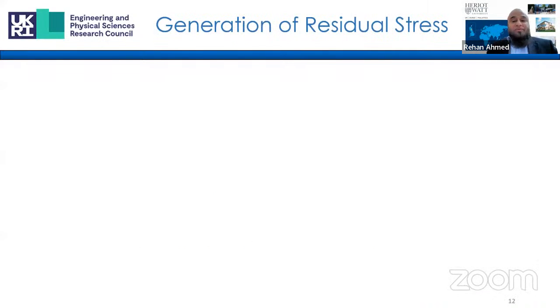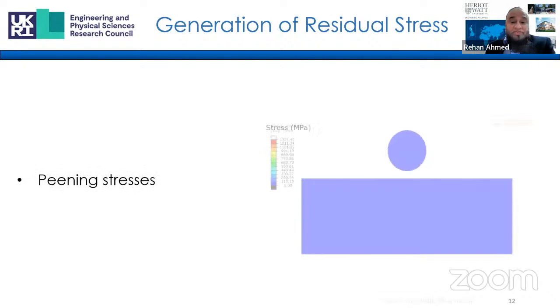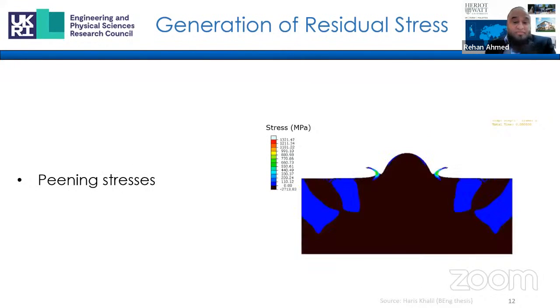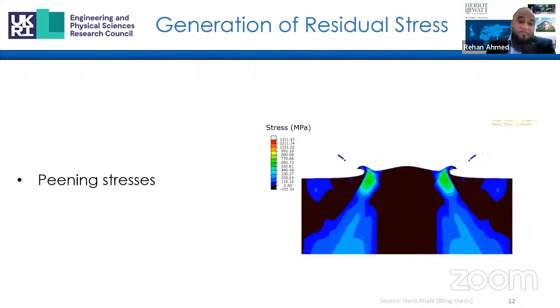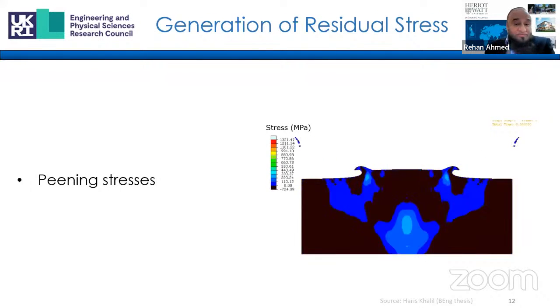So we have now established that the residual stress profile in thermal spray coating is dependent upon the type of stress measured and is influenced by the changes in coating process, measurement technique, changes due to the environment such as bioactivity or mechanical or the wear process. We can now categorize the mechanism of residual stress generation in thermal spray coatings as those caused by the peening effect, the quenching effect, and the differences in the coefficient of thermal expansion.